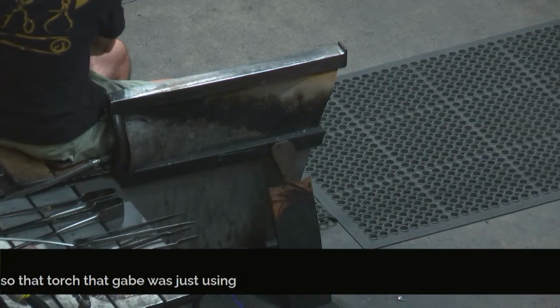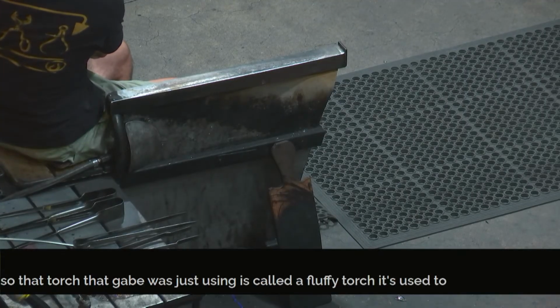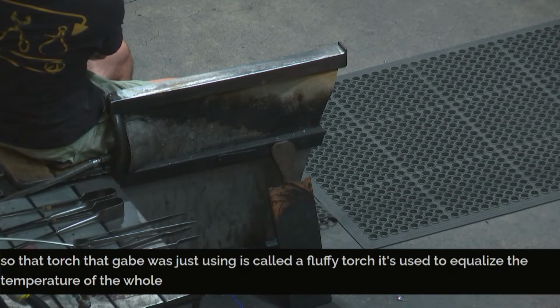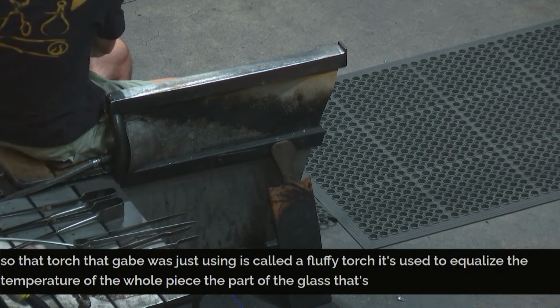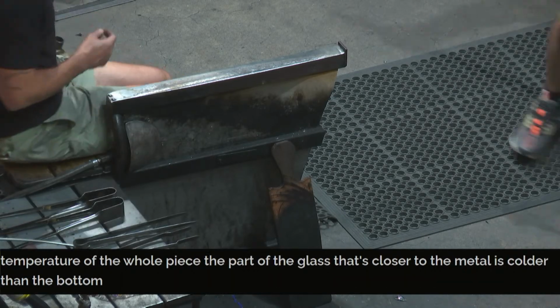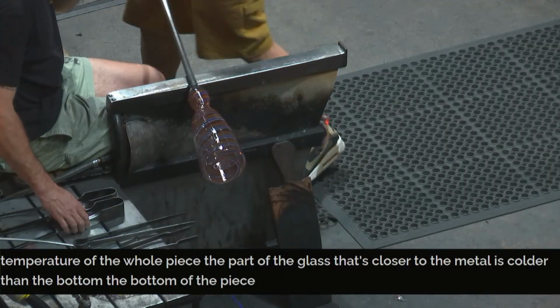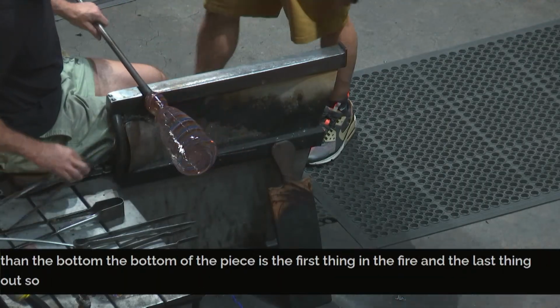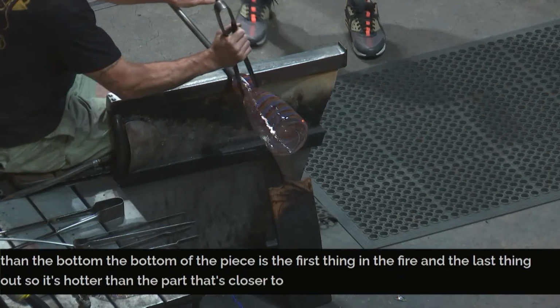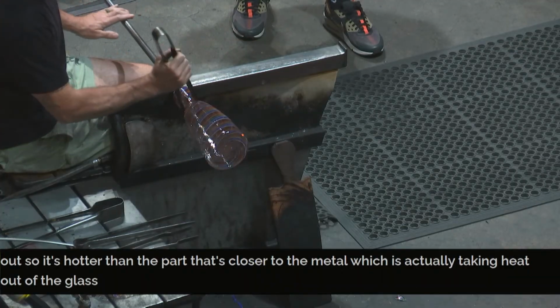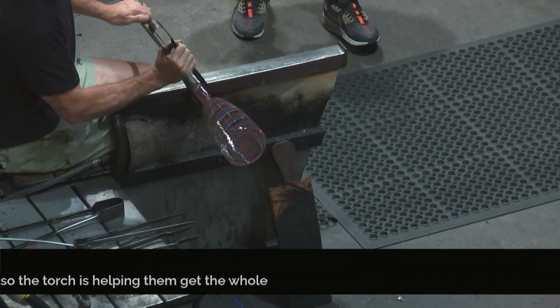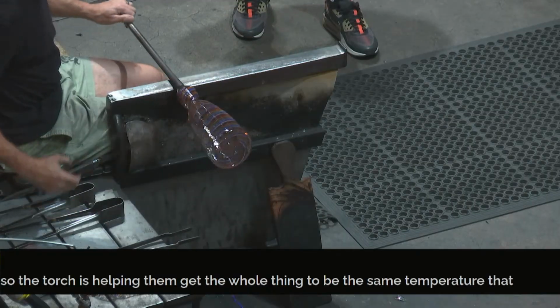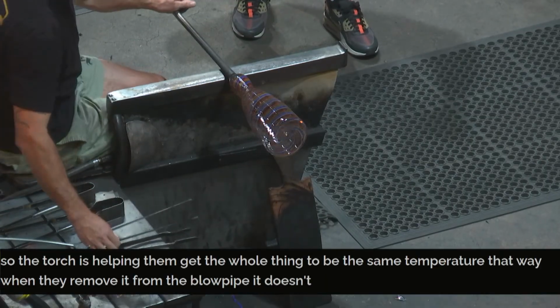So that torch that Gabe was just using is called a fluffy torch. It's used to equalize the temperature of the whole piece. The part of the glass that's closer to the metal is colder than the bottom. The bottom of the piece is the first thing in the fire and the last thing out, so it's hotter than the part that's closer to the metal, which is actually taking heat out of the glass. So the torch is helping them get the whole thing to be the same temperature. That way when they remove it from the blowpipe, it doesn't crack.